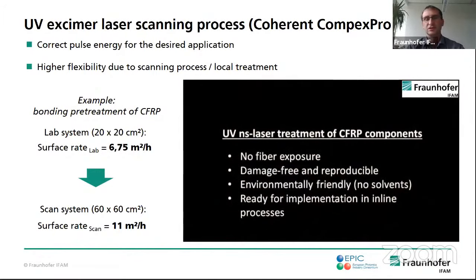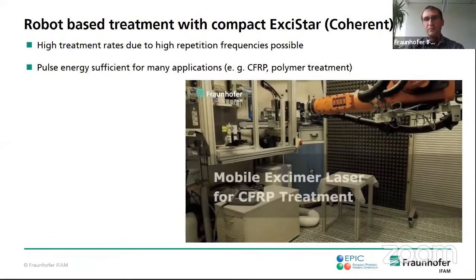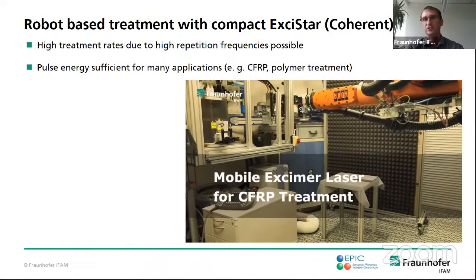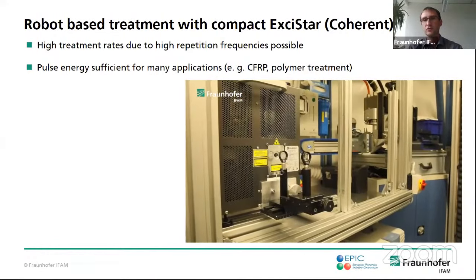And therefore, you typically use a lower amount of output energy for your laser treatment than the whole system could apply. So in this case, we used a Compex Pro, and we applied typically 40 to 50% of its complete output power. But with changing the shape of the laser beam, and also with the scan head, we were able to increase the surface rate from roughly 7 square meter per hour to up to 11 square meter an hour.